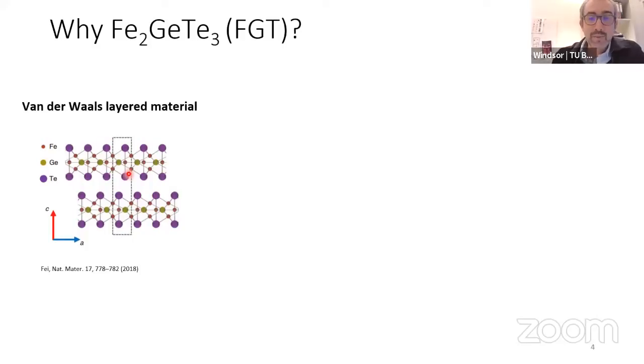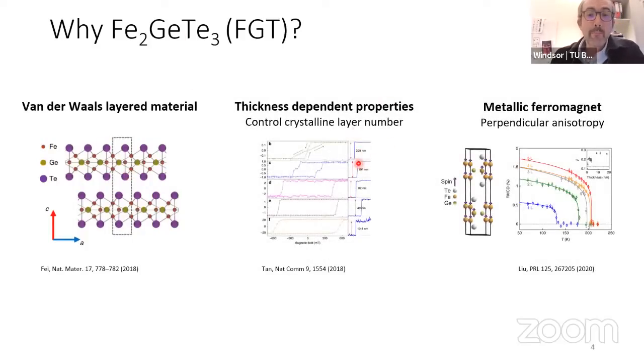Now, in extension in 2D magnets, this is quite apparent because we have many more properties that can be manipulated just by changing this crystal structure, just by removing the amount of layers. Here I'm showing an example where you can see that the hysteresis loop of this material changes, with the coercivity essentially changing as you reduce the amount of layers. Here you can see that the TC is changing. In this case, it's reducing, so not amazing. And FGT in particular also remains a perpendicular anisotropy system, meaning that it is useful for many applications. Well, this used to be a very big thing where people would try to induce stronger and stronger perpendicular magnetic anisotropy. So that's a bit on FGT.